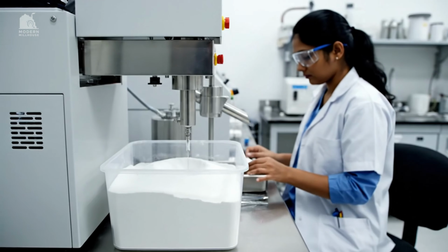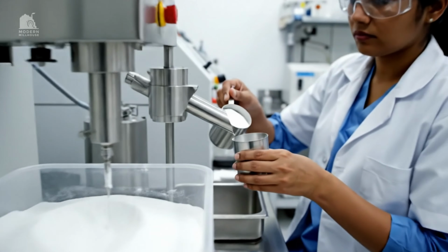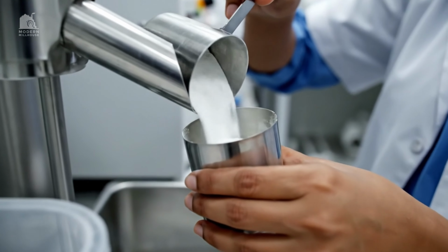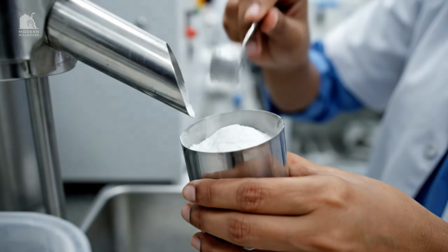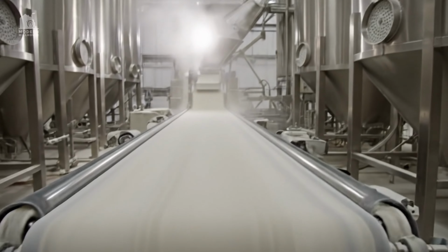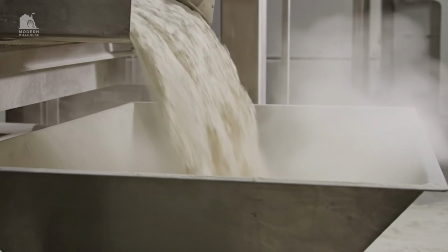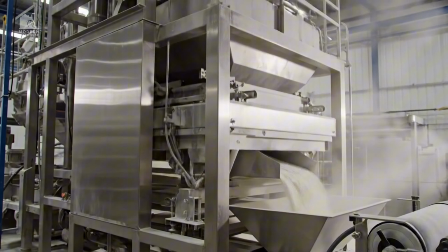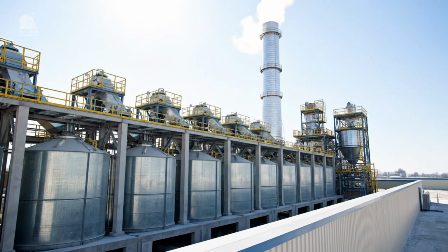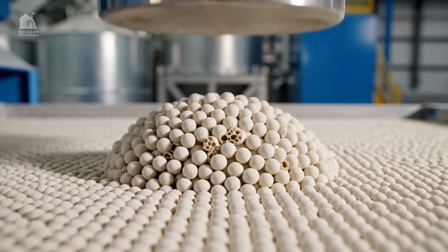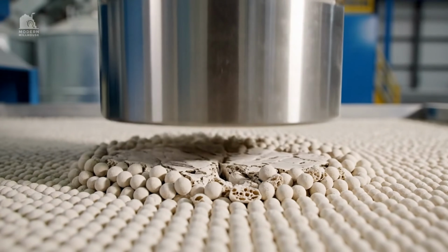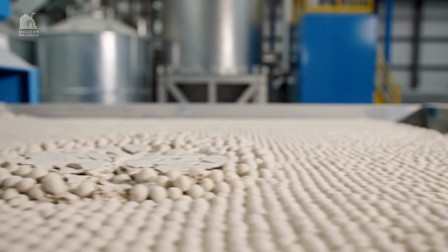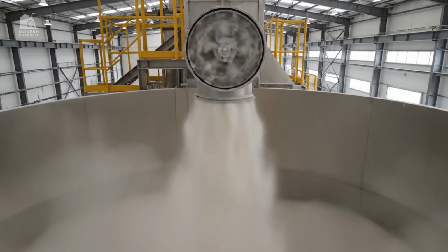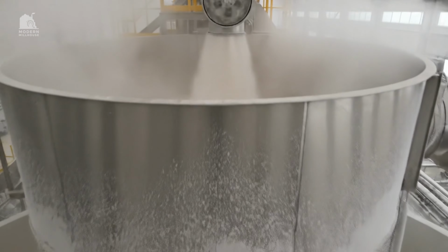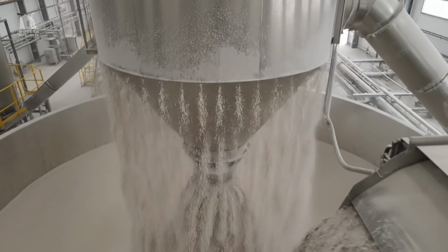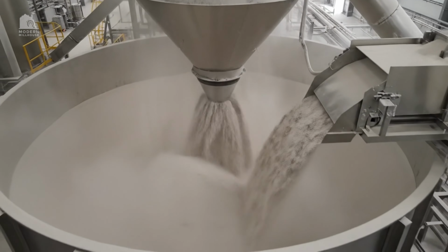To keep flow smooth, silos use vibration or aeration, so powder does not bridge or form tunnels. The finished powder moves to silos that feed the press line steadily, like flour feeding a bakery. Spray drying also sets the internal structure of each granule. A good granule fractures and collapses under press pressure, filling voids and creating uniform density. A bad granule resists compaction, leaving hidden pores that become weak points or cause differential shrinkage.